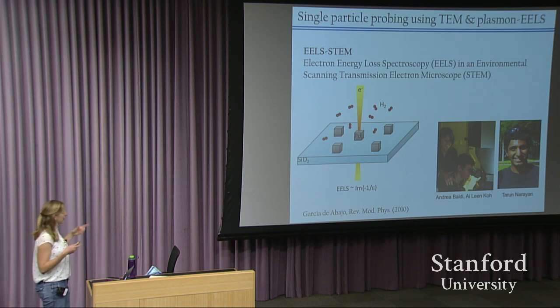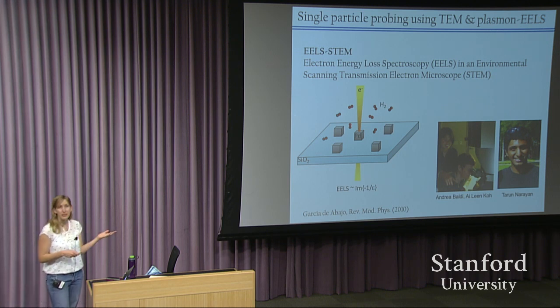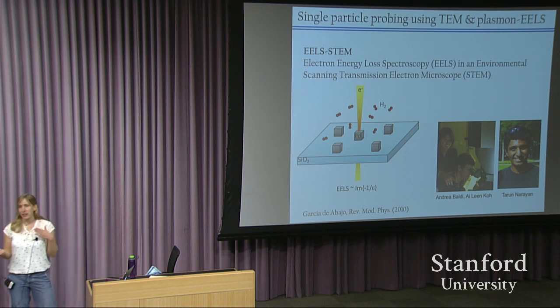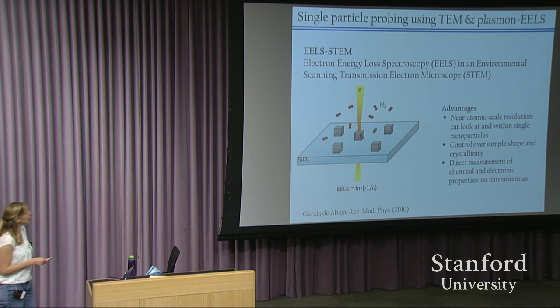And it turns out that the various modes that get excited at different wavelengths are proportional to the permittivity of the material, or essentially the dielectric constant. So the electron energy loss spectra signal is proportional to the imaginary component of 1 over the permittivity. So EELS is a really good signal of the electronic structure of a material. And that's something that you can imagine gets changed when there's either a new phase or when there's hydrogen intercalating into the palladium.